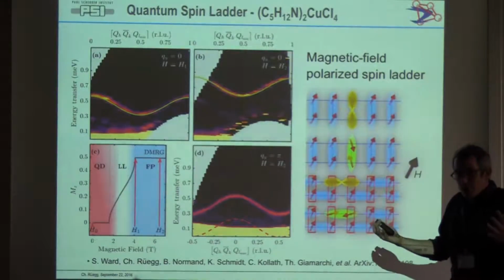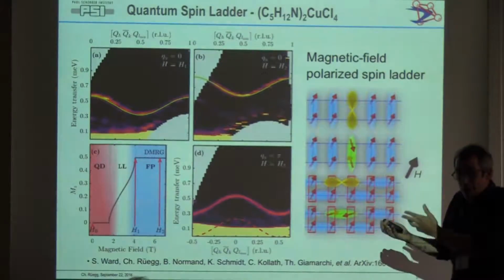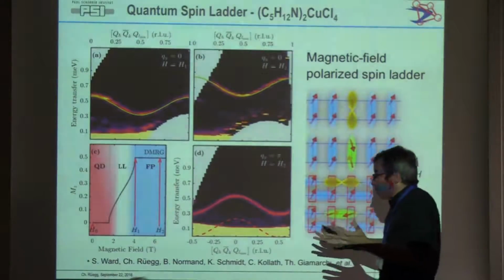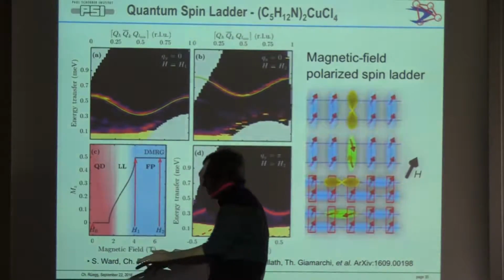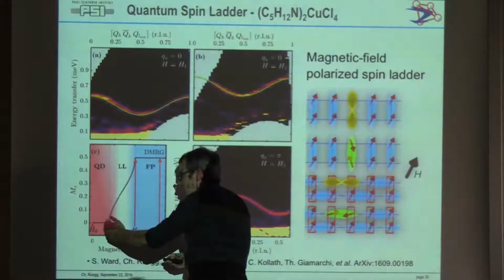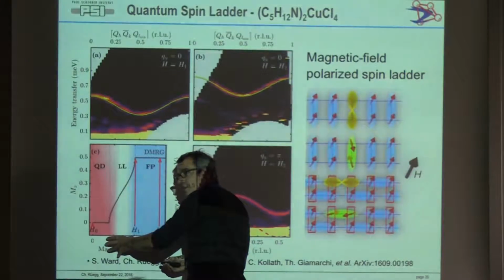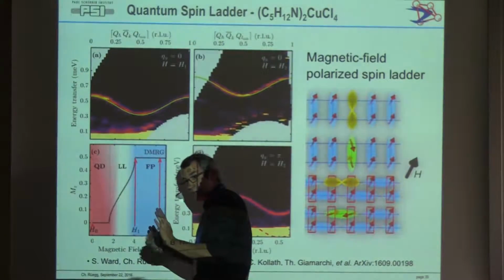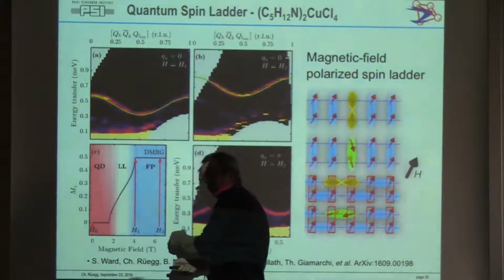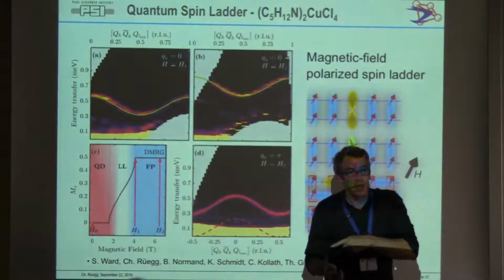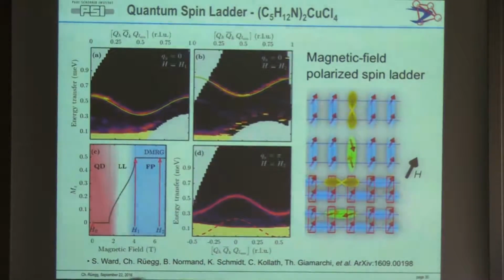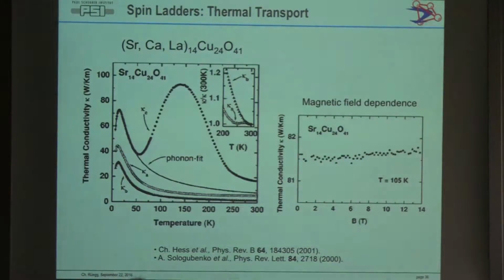So now in terms of, if you look for spin transport, and I don't know how to build the device, of course, but such a system is very beautiful. I mean, you essentially start here with a gap. You close the gap, you reach a Luttinger liquid regime, where you can tune basically the density of particles. You can go to the fully gapped saturated regime. And you can measure all of these different regimes in one sample in principle. That's quite cool. So how about thermal transport?